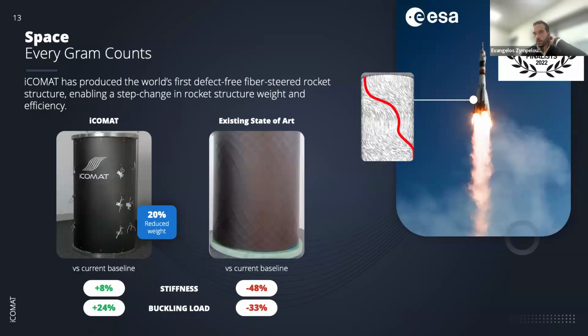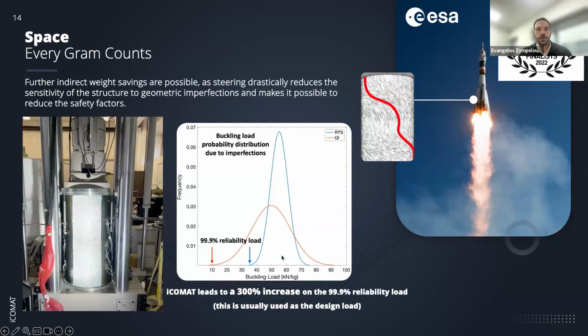And we've done a lot of work also on similar structures for space, which was one of the very first applications of fiber steering. And we've recently produced and tested the world's first fiber steered cylinder that outperformed the best straight fiber design. The benefits were very well documented in the literature, but nobody could realize them in a test result because of the defects that you get when you manufacture fiber steered structures, which you see here. But we actually did a defect-free cylinder. We achieved 24% higher buckling load, which translated in about 20% weight reduction. And crucially, we massively improved the reliability load by 300%.